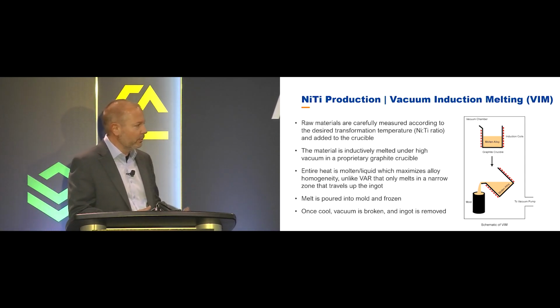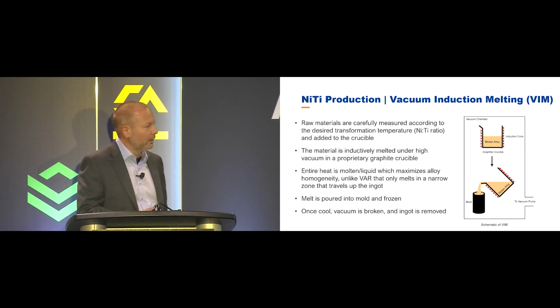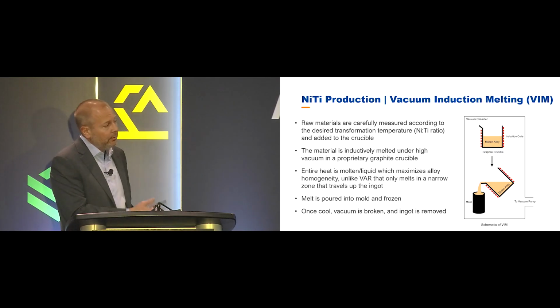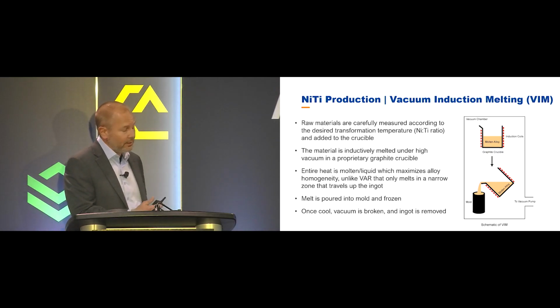So over the years, we've really developed a grade of graphite to work for us. We do pick up carbon from it. It does dissolve a layer of the crucible, but to us, it's not a bad thing. We end up with a very fine distribution of inclusions.